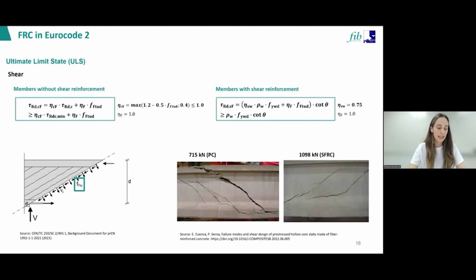If we talk about the shear, steel fibers contribute by controlling the opening and propagation of inclined cracks generated by shear. So instead of developing a single critical crack, steel fiber reinforced concrete members tend to exhibit a more distributed and stable cracking pattern, which improves aggregate interlock and enhances the shear transfer capacity across the crack section. Within Annex L, the fiber contribution is introduced through an additional resistant term associated with the ultimate residual tensile strength. At the same time, the code introduces this reduction parameter, eta, to account for the fact that the fiber contribution is not fully additive to the concrete or the reinforcement contribution. As shown in this experimental campaign, the reduction of the cracking pattern in members with fibers may become very, very